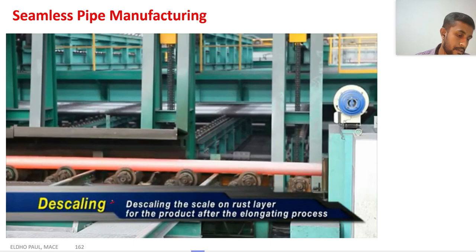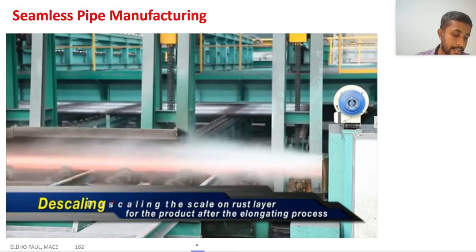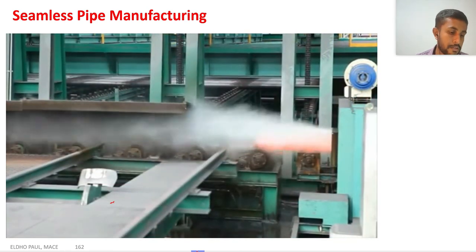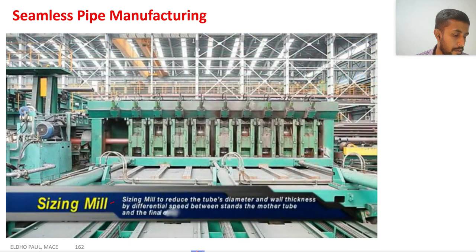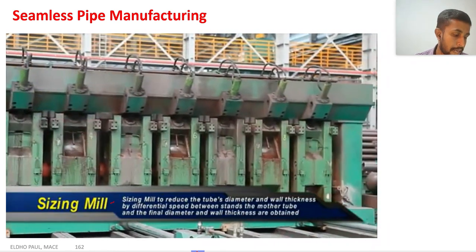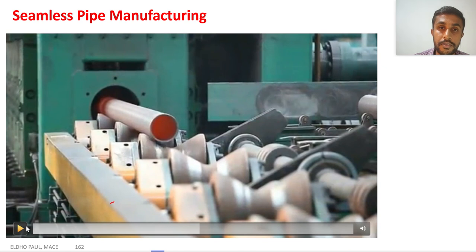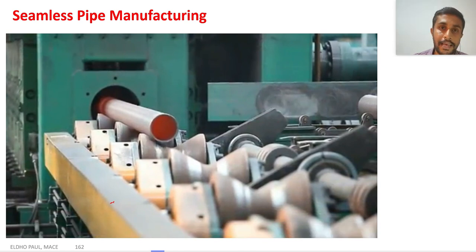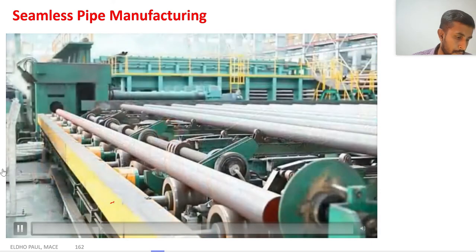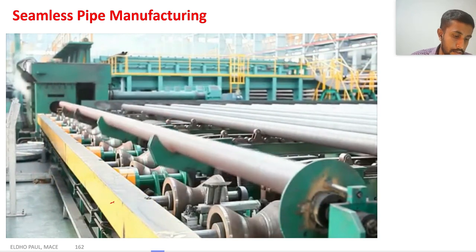Then we have to do descaling as an intermediate process, because during this process the hot workpiece may react with the oxygen and other atmospheric gases and form scales. And during the cold rolling process, these scales may affect the workpiece or form different defects on it. So we have to remove these scales using the descaling process. By spraying water under high pressure, we can remove the scales. So we get the final pipes.